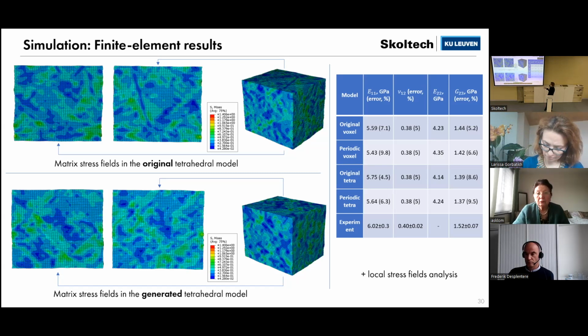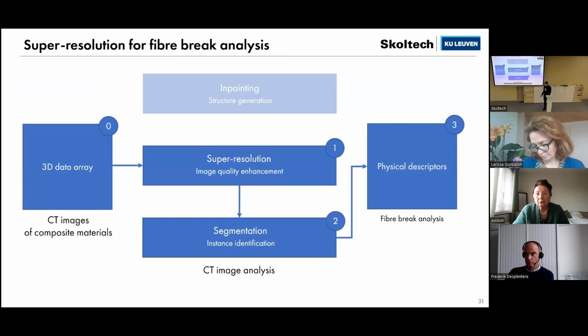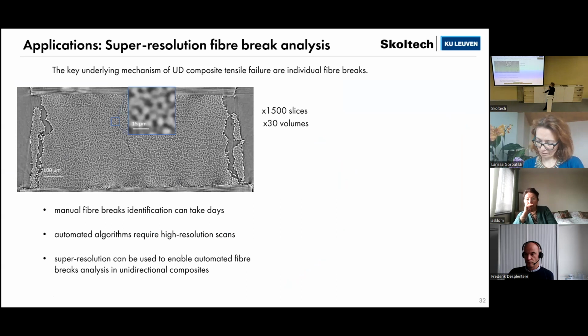Also, local stress fields were analyzed. And the second validation case for these algorithms is super resolution for fiber break identification, where we don't use inpainting because we don't need it. And why do we need this fiber identification? Because here is an example of time-resolved synchrotron CT scans. These are large scans with a lot of fiber breaks in them, and they were scanned 30 times during the mechanical testing. To analyze them, we don't have any algorithms to identify fiber breaks automatically, and manual identification can take days.